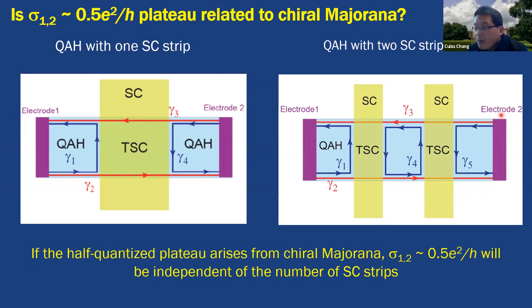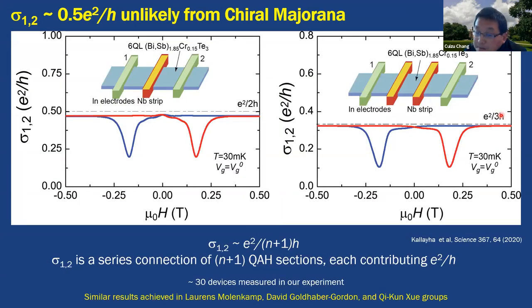So we performed the transport measurement. Here are the transport results. We can see the sample we used is six quintuple layer chromium-doped bismuth antimony telluride. In this sample, it shows the half-quantized Hall conductance plateau, just in the 2D regime. We can see that in this quantum anomalous Hall and niobium with only one niobium strip, it shows e squared over 2h, similar to what I introduced in my previous slide. If you put two niobium strips, it actually becomes e squared over 3h rather than always keeping at e squared over 2h.